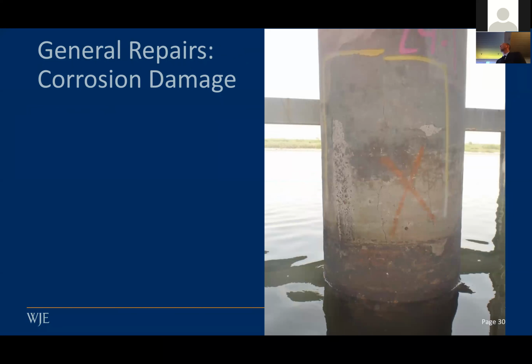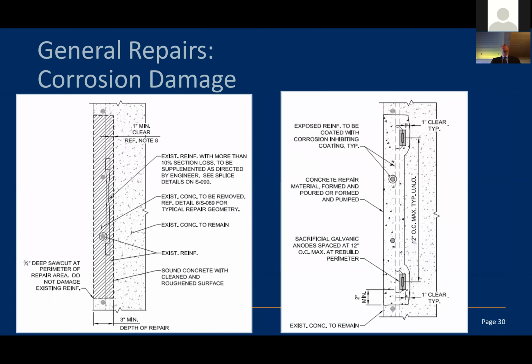So I just wanted to quickly summarize some of the repair techniques that we used to mitigate the damage. This is an example of a delamination. So it's at the initiation of corrosion and it needs to be addressed. We used just a typical partial depth repair. This is something that you might see in ICRI or some other ACI documents about how to do, but it involves demoing out all the unsound concrete, getting behind the bar, cleaning the bar, and then putting some corrosion inhibiting material on the bar. And in this case, we're going to also install some galvanic anodes to mitigate future corrosion. So those are a way of providing localized corrosion protection for the repair so that they can last longer.